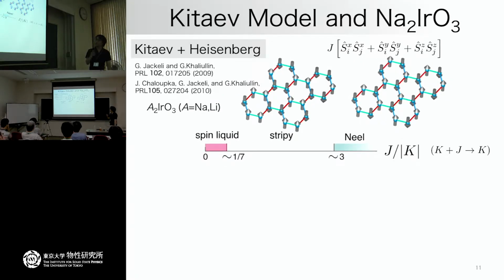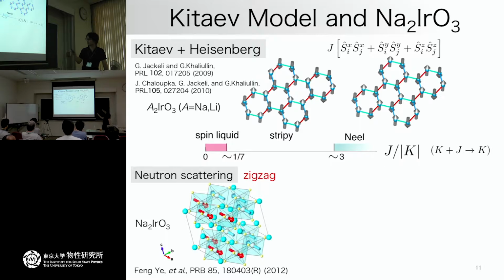And if you look at the real compound, as I already said, usually we can have a Kitaev coupling. In addition to the Kitaev coupling, we can have a Heisenberg coupling also. This situation is examined by these papers by George Jackeli and their collaborator Giniyat Khaliullin. And what they found is something like this. If the Heisenberg term is small enough compared with the Kitaev coupling, then we can enjoy the spin-liquid physics. But if we introduce a further larger exchange coupling in addition to the Kitaev coupling, then we will have a magnetically ordered ground state.